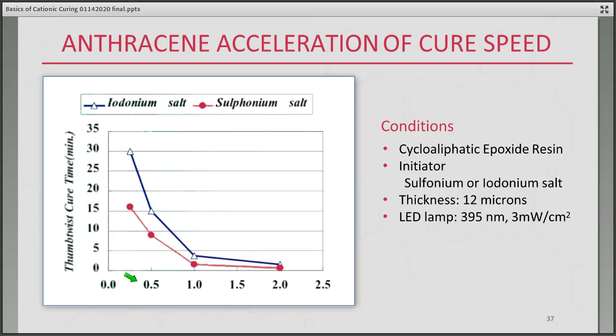By adding a little bit, 0.5%, we drop iodonium from 30 to 15, cutting it in about half, a little bit less for the sulfonium. Going up to 1% of anthracene derivative in your formulation, you've now dramatically reduced your cure time. This is using a UV LED lamp at 395 nanometers.